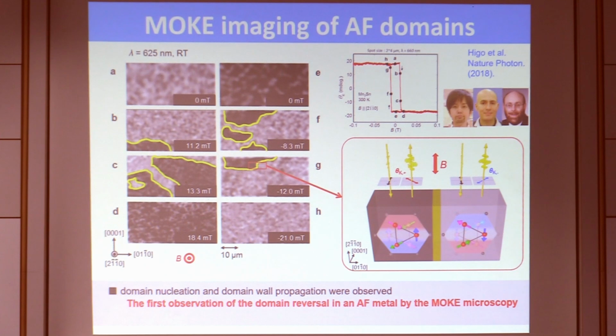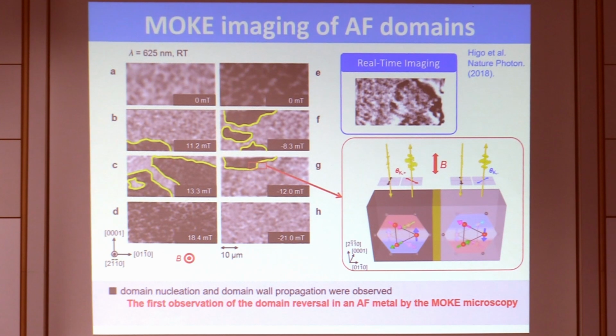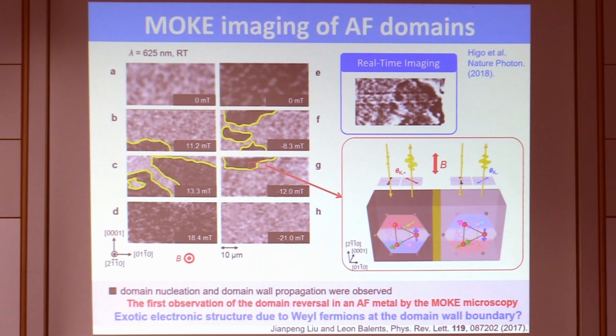This is quite interesting. Another thing is that one should be able to use this Kerr effect for real-time monitoring of these magnetic domains. And in fact, one can see such a change of the magnetic domain, domain wall propagation. Another interesting point is that this magnetic domain wall is actually an edge of this magnetic Weyl semimetal, so there might be some additional electronic structure at the domain wall.